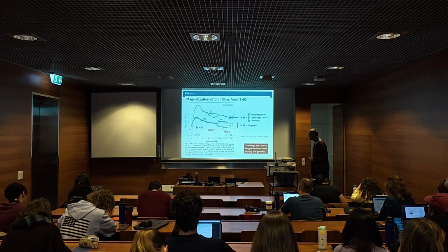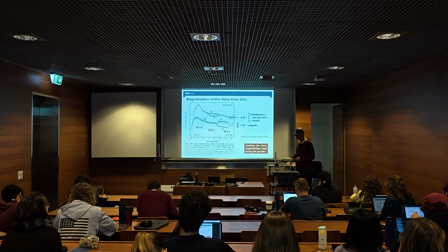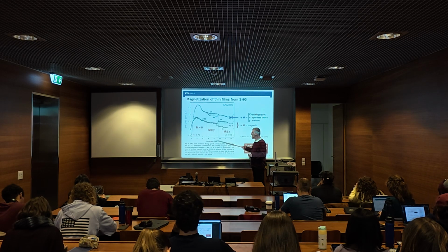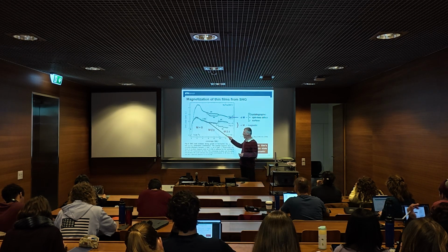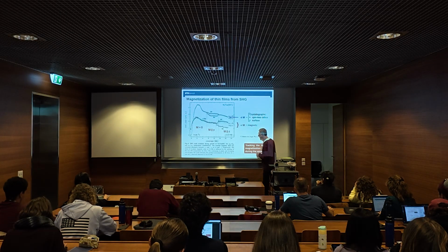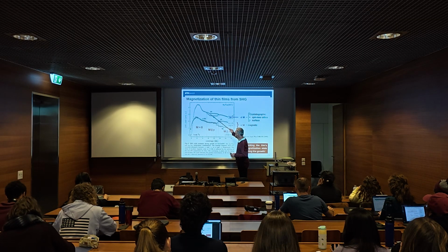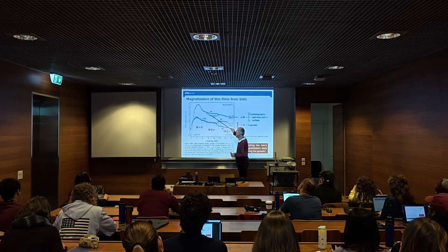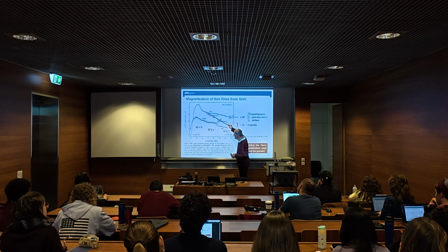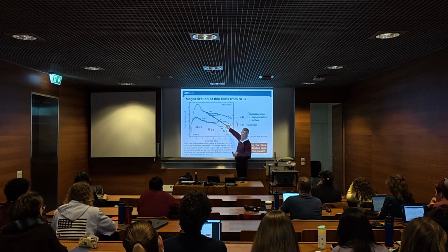And this is one of these typical experiments that was too early to be successful. So they showed something really nice. They grew a nickel film, a ferromagnetic nickel film. And while it was growing in that chamber, they measured the frequency doubled emission, so they measured the second harmonic intensity. So they could see 0, 2, 4, 6 monolayers, and they measured it in a magnetic field, for magnetization up and down. And then at 5.5 monolayers, you suddenly get a magnetization dependent splitting in the signal intensity. So this is when the sample actually gets ferromagnetic.